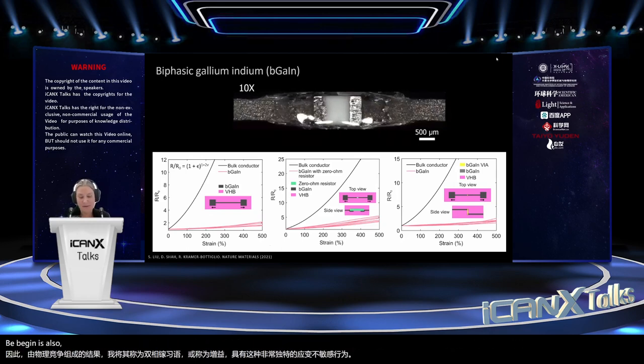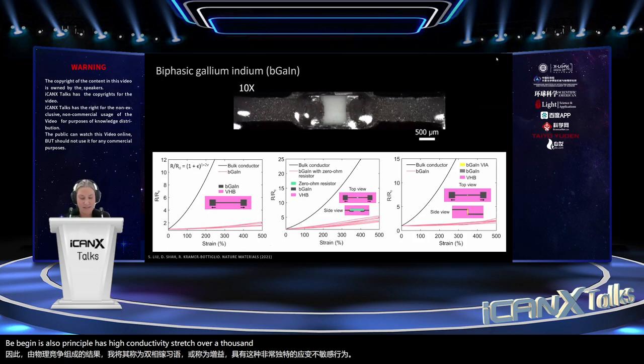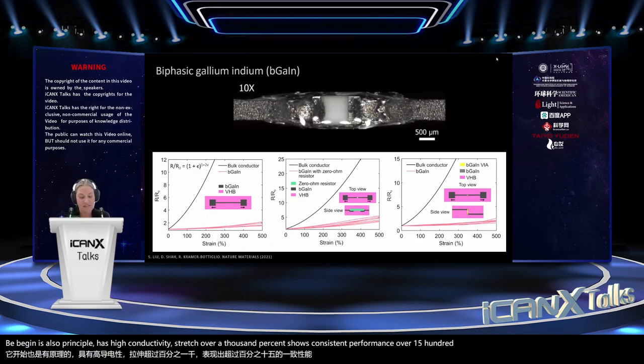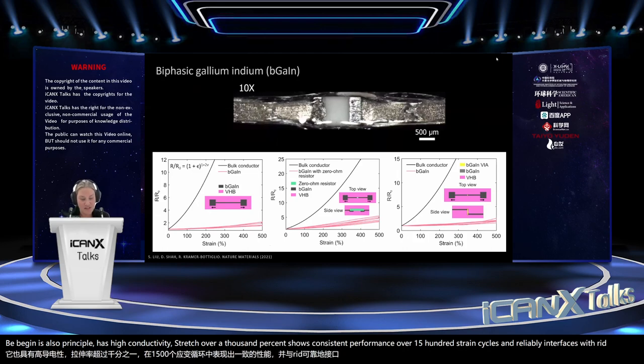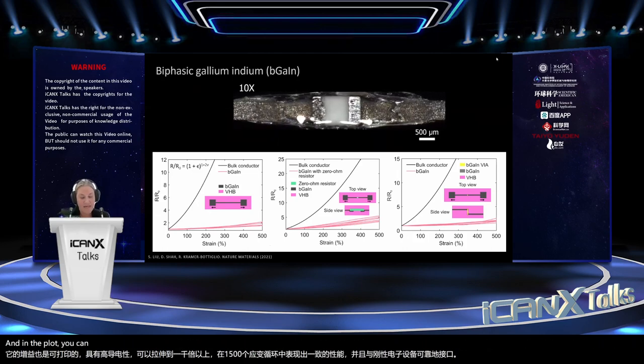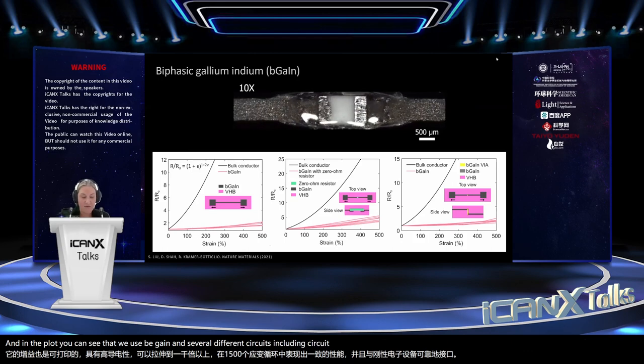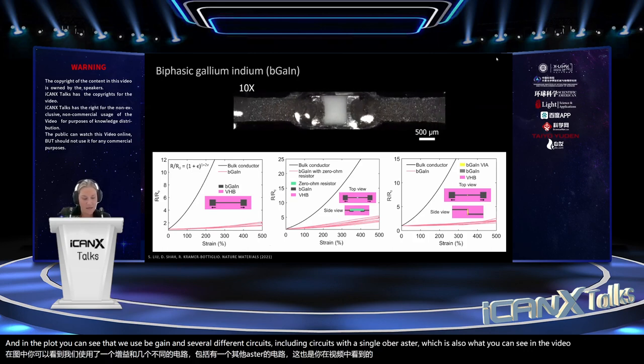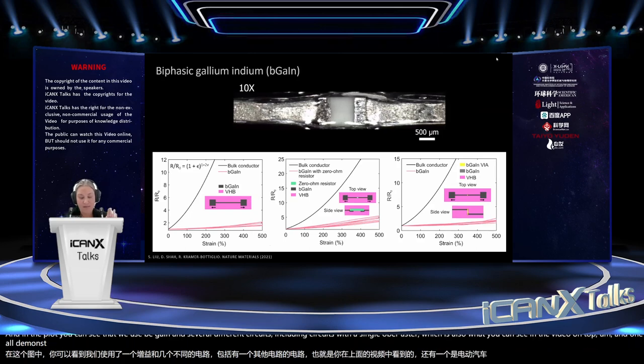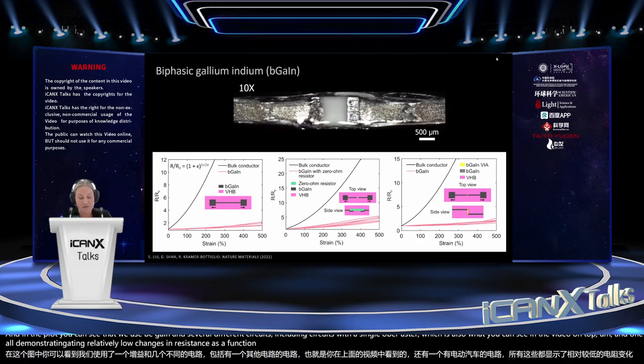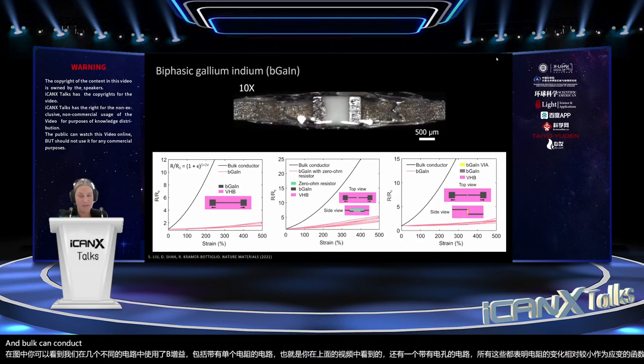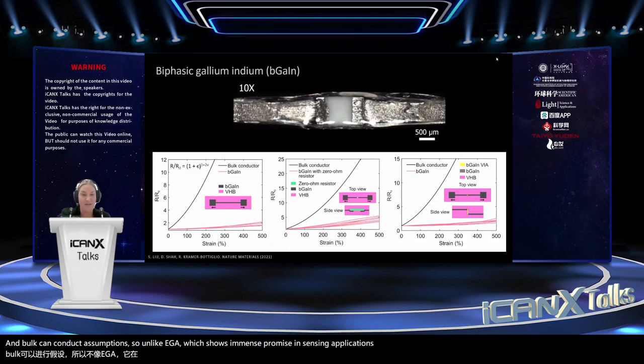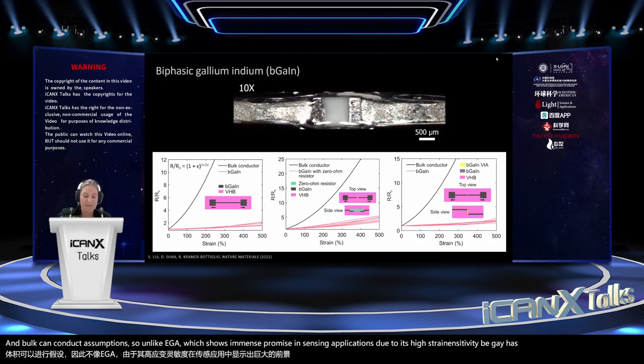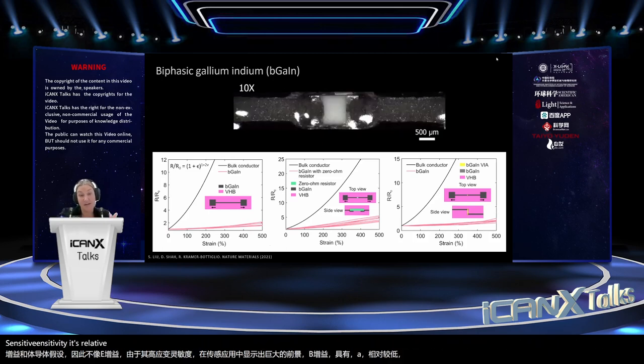BGaIn is also printable, has high conductivity, can stretch to over 1,000%, shows consistent performance over 1,500 strain cycles, and reliably interfaces with rigid electronics. And in the plots, you can see that we use BGaIn in several different circuits, including circuits with a zero-ohm resistor, which is also what you can see in the video on top, and one with an electrical via, all demonstrating relatively low changes in resistance as a function of strain when compared to eGaIn and bulk conductor assumptions. So unlike eGaIn, which shows immense promise in sensing applications due to its high strain sensitivity, BGaIn has a relatively low sensitivity. Its relative strain insensitivity makes it more applicable to soft circuit applications.